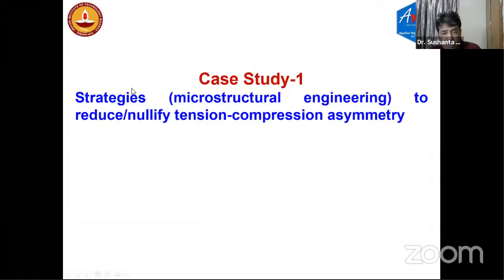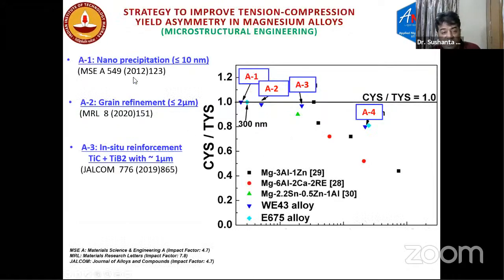So magnesium shows poor tension to compression yield asymmetry. We addressed that by engineering, by imparting different kinds of microstructural constituents during manufacturing. For example, here we need tension to compression yield asymmetry to be 1. However, all the published papers have shown that there is a significant yield asymmetry in this case. In different approaches, initially we did nano precipitation. By using nano precipitation, we overcame the tension to compression yield asymmetry problem. By using grain refinement, it became 1. When the grain size became less than 2, there is no tension to compression yield asymmetry. When we integrated in situ reinforcement in A3, we also did not find any tension to compression yield asymmetry.